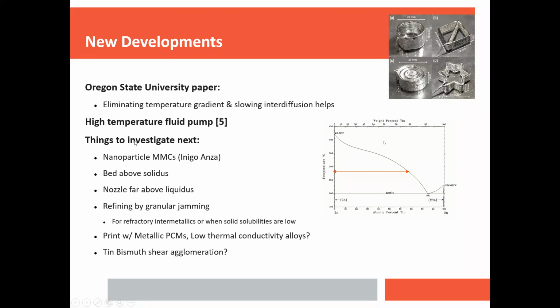I mean, we could continue down the road that Oregon State University showed, making a nanoparticle metal matrix composite instead. Also, I want to mention my friend Inigo Anza in the Metals Processing Institute was working with an aluminum nitride and aluminum composite that had similar viscous properties a couple of years ago. And he also suggested printing that composition. Oregon State University's paper proves the concept he suggested at the time. And then, just different process parameters, like having the print bed above the solidus temperature to further alter the temperature drop across the nozzle, or having the nozzle far enough above the liquidus that the metal remains molten. Anyway,